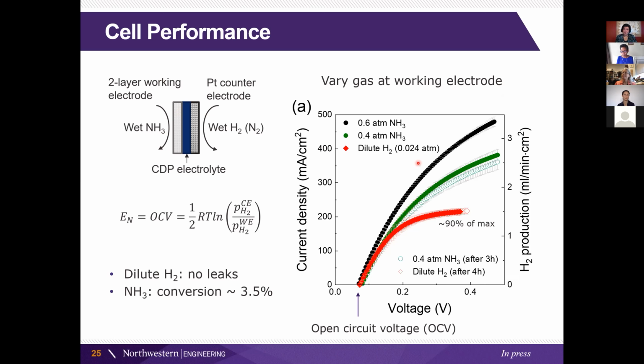And so we did a quick test to make sure that our cells operate with hydrogen. We get an open circuit voltage here that matches what you expect based on this Nernst equation. So that means we have 100% dense electrolyte because we get the right voltage. And then as we drive the hydrogen through, we are unable to get more current once we're at around 90% of the maximum.